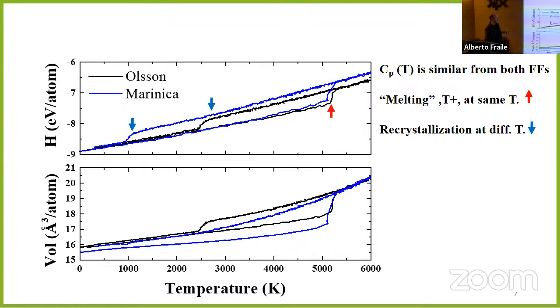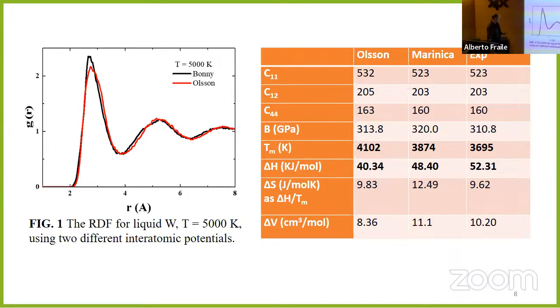But what is not the same is the recrystallization when you do this kind of cycle. So the 2 potentials are similar and different depending on what we look at. Also, they are different if we look at the jump in volume here at melting. We can compare this with the experiment and know more about which potential looks better. We can calculate the structure of the liquid. In both cases, it's pretty much the same.